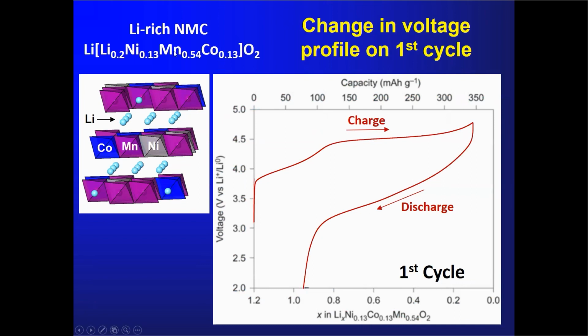So the compound that I'm going to talk about quite often as a nice model of these sorts of so-called oxygen redox or lithium-rich materials is the one that you see in the top left-hand side here. It's a layered transition metal oxide. Instead of having cobalt in between the square brackets, which represents the ions on the transition metal sites, you have a mixture of not only nickel, manganese, and cobalt, as one has in the mixed NMC materials, but also lithium. So this is a lithium-rich material, and this is important that you now have lithium on these transition metal sites. So here's a representation of the crystal structure. Here are the lithium layers, the alkali metal layers, and here are the transition metal layers with cobalt, manganese, nickel, and also lithium.